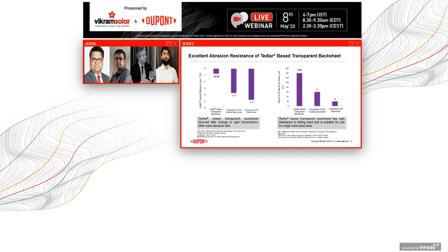We also look at abrasion losses, and this was mentioned by Ivan. The way we measure it is through an ASTM standard test, which actually is much harsher than any field condition that the modules would see. This is essentially 100 liters of sand and surface cleaning.